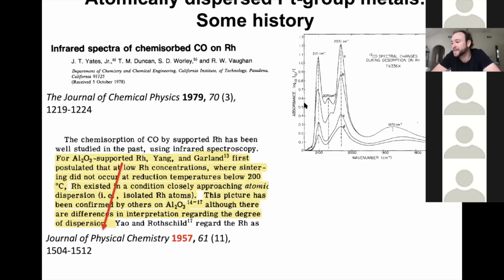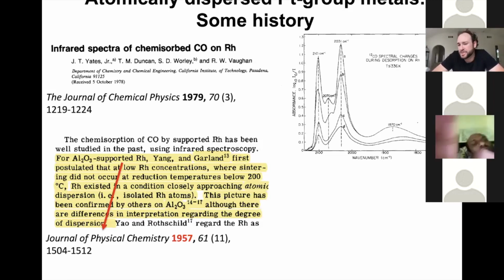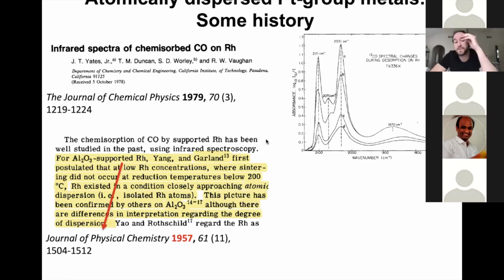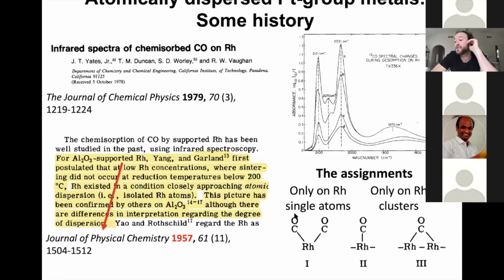This paper specifically had very nice infrared spectra in here, and I'll talk a little bit more about this in a few slides, but when you adsorb CO to a catalyst where rhodium has been dispersed on an oxide, you see all sorts of different stretching bands. This should tell you that there's lots of different coordination environments that CO is binding to. And it's interesting to try to understand what those coordination environments are. So in this paper, Yates nicely tried to identify a few different coordination environments, those that can happen only on single atoms and those that can happen only on clusters. So this is just to give you perspective that there's a lot of information out there about this class of materials, and it's not just a new field. There's actually a lot that's been done previously.